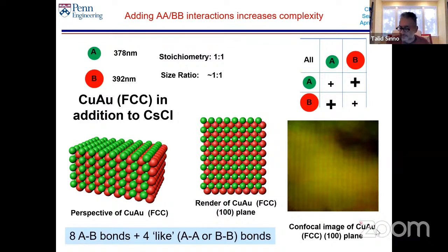And I'll refer to this as the atomic analog: copper gold. So we had cesium chloride, now we have copper gold. Copper gold is an FCC, and again, I'm alternating red and green, okay? And an FCC, which is a close-packed 12-fold coordinated system, each A particle will have bonds to 8 Bs and 4 As. And each B particle likewise will have bonds to 8 As and 4 other Bs, okay?